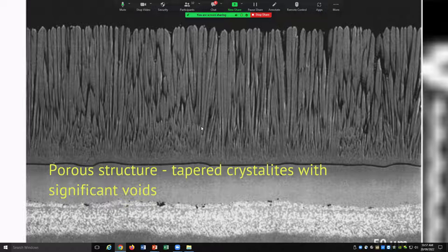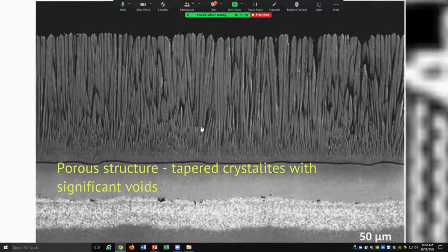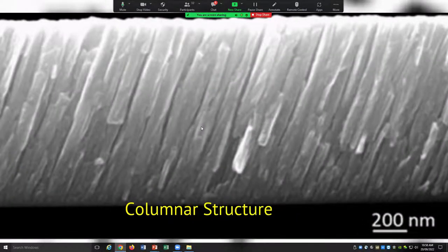So for an optical coating where you're trying to filter out a particular wavelength, as soon as you vent this to atmosphere, you've got water in there, your optical performance would change significantly. So this would be a bad thing. So as you turn up the energy, so drop the pressure or increase the substrate temperature or put in other forms of energy, you can get denser coatings.